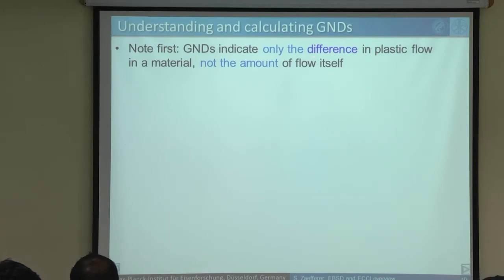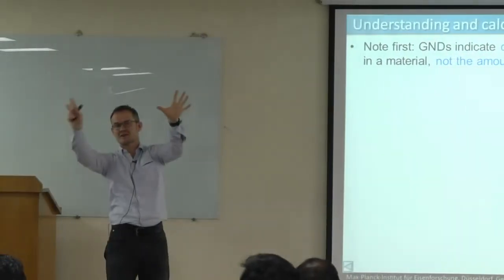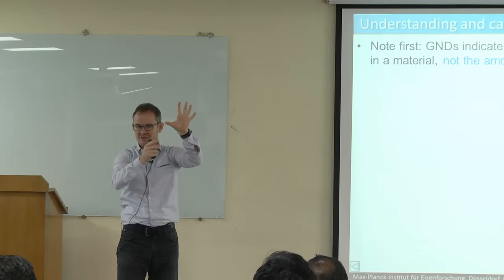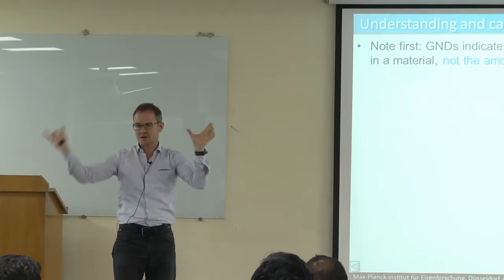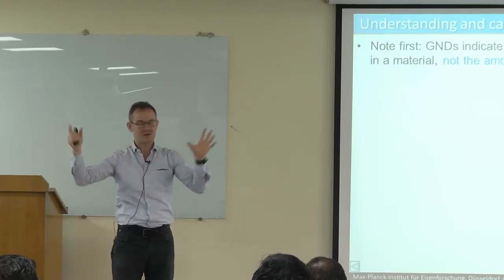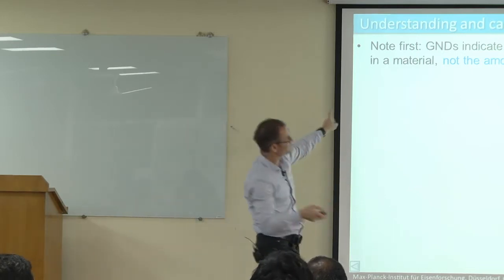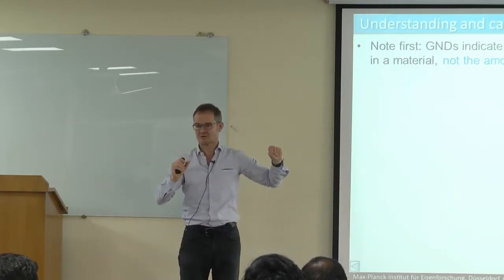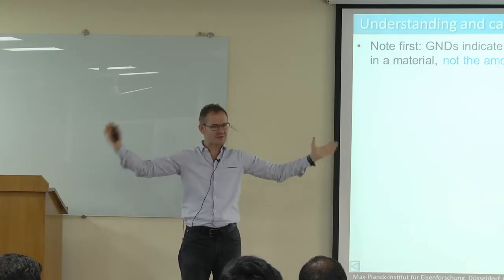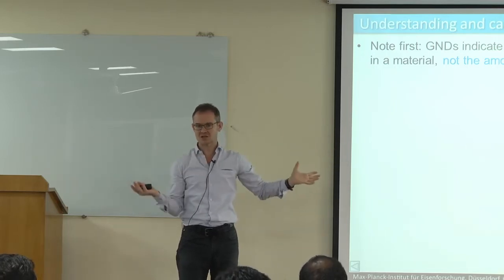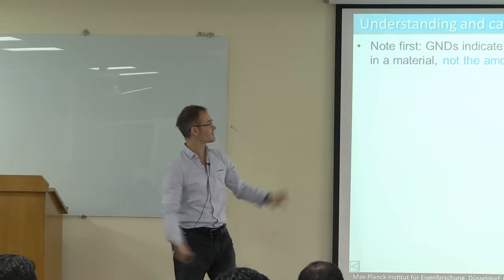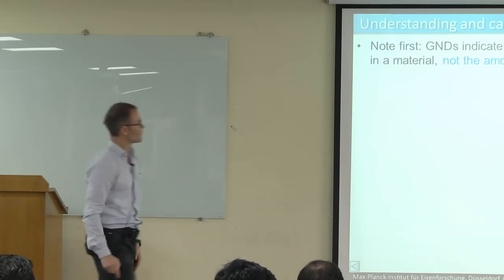GNDs indicate only how much different is plastic flow in different areas of a grain. If you have a whole grain, and in this corner the crystal rotates like that, and in this corner the crystal rotates like that, in between you get GNDs, which are indicating that the crystal deformation is not homogeneous. So GNDs indicate the difference in plastic flow and not the total amount of plastic flow. You could deform a crystal very much and not create any GNDs, yeah? If it's homogeneous. If it's heterogeneous, it's a different story.